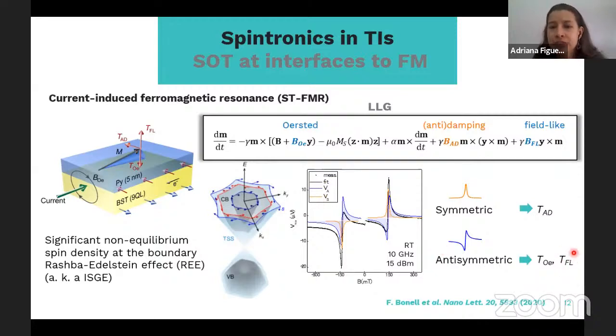And the field-like torque is the one that you're interested in, because it comes as a consequence of the Rashba-Edelstein effect at the interface. And then what you want to do is to optimize that torque to make sure that it comes from the topological surface states, so that you exploit those properties of the TIs, right?